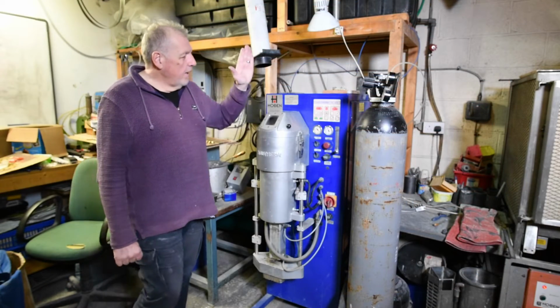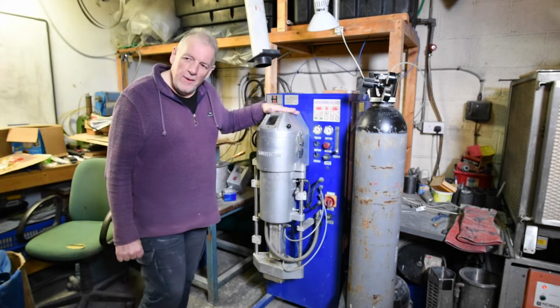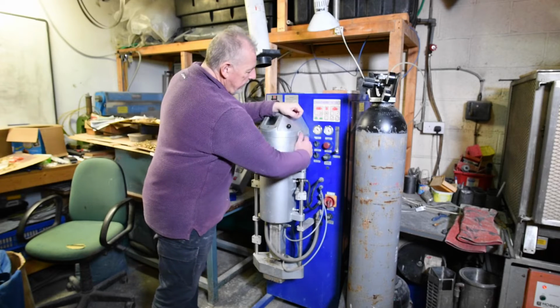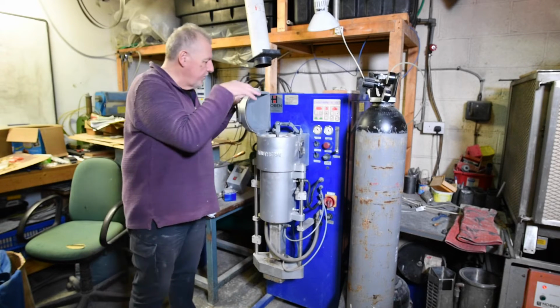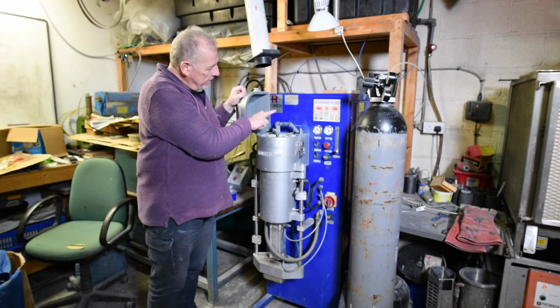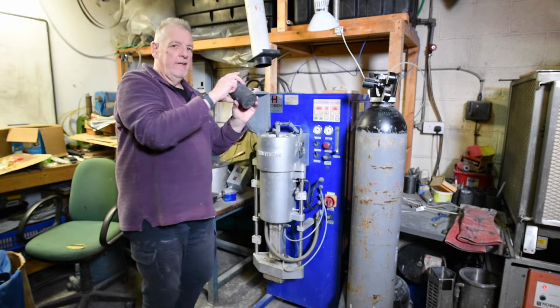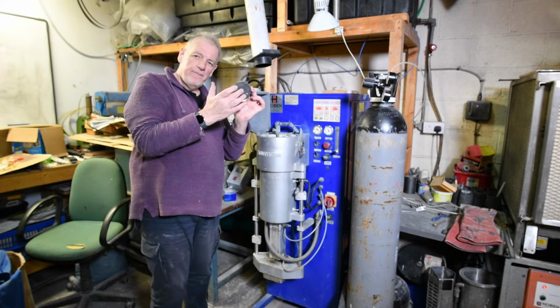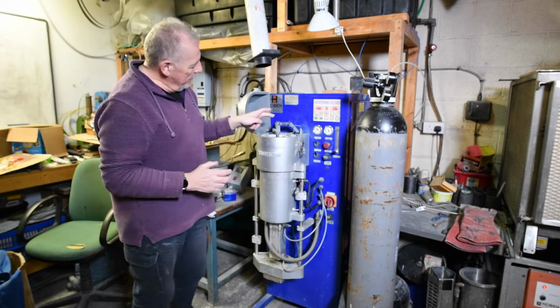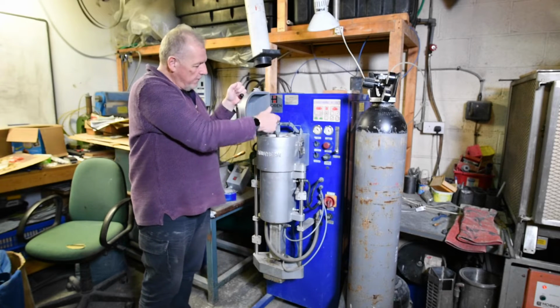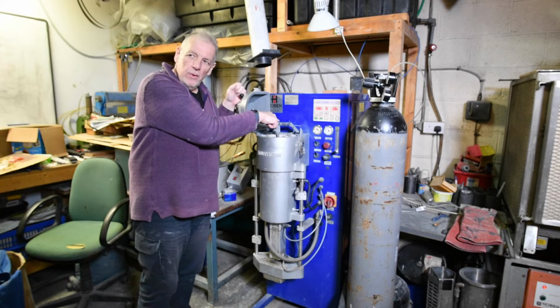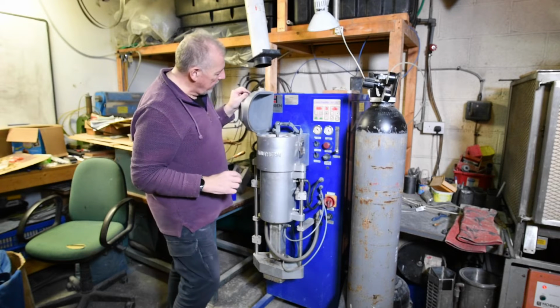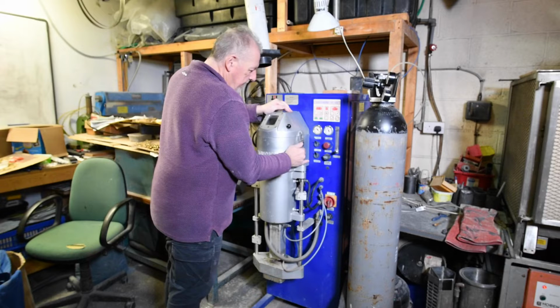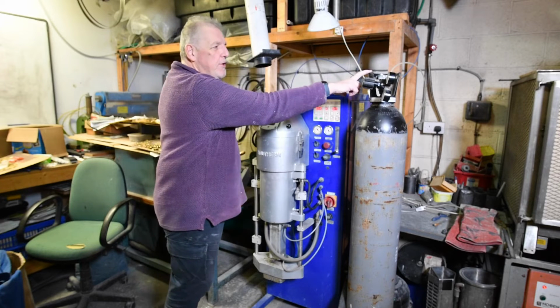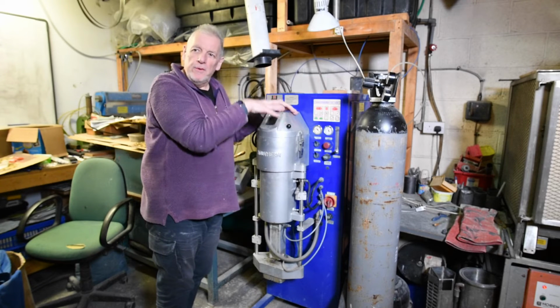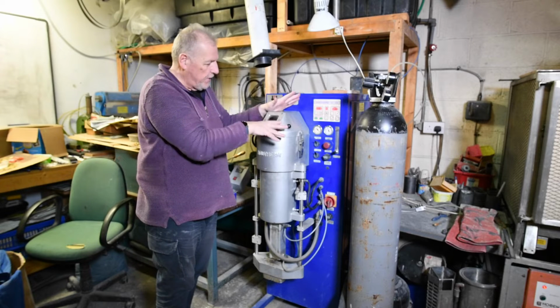Okay. The metal is then put into the crucible inside the casting machine. This is the casting machine that we have here. Inside is a crucible, and the crucible actually has a hole in the centre, and there's a rod. It's a graphite crucible, a graphite rod, which is blocking that hole in the centre of the crucible. The metal is placed inside, lid is closed and clamped down. There is a gas blanket of nitrogen over the top to keep down any oxidation possible inside the chamber.